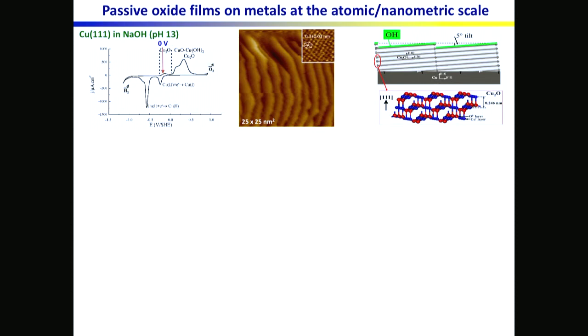Minimization of the interface energy by a growth tilted with respect to the base surface, and minimization of the surface energy. So these are 3 critical factors for the stability of the oxide. So this is the model of the surface here, and in addition, there are OH groups adsorbed at the surface. So we did similar work on other metals. I'm going to show 2 other examples to show similarities and differences.